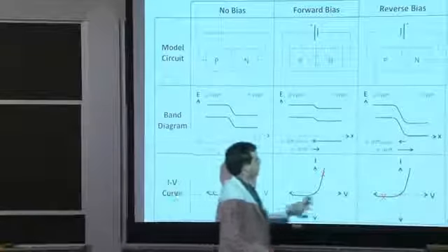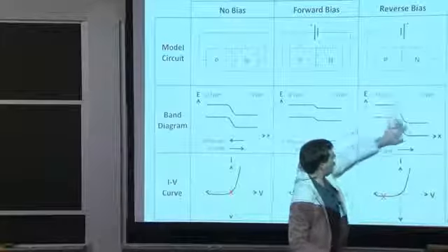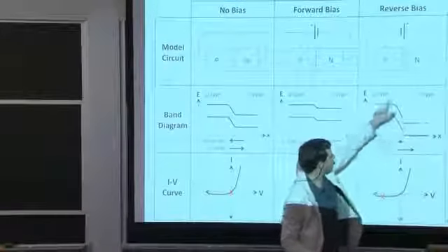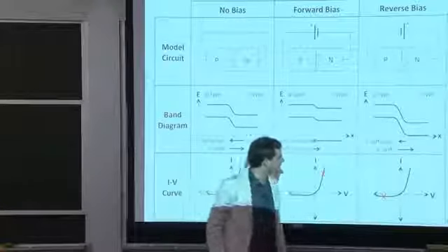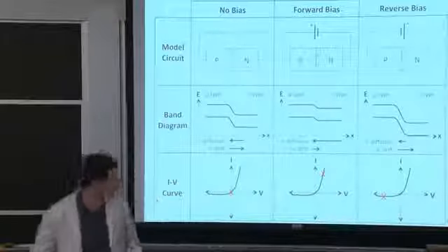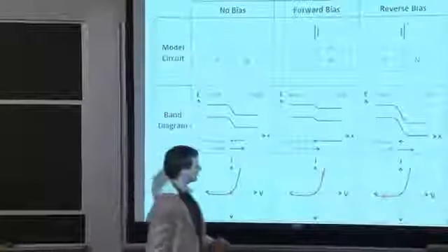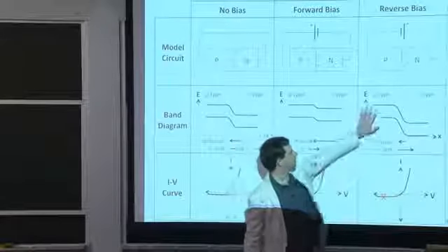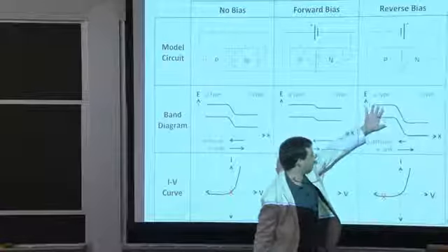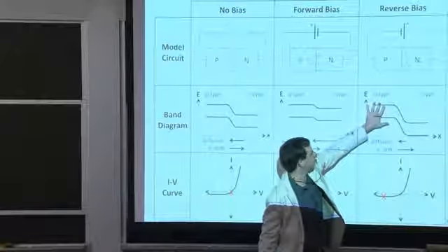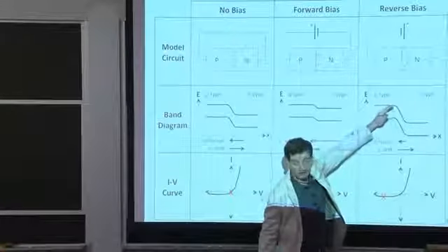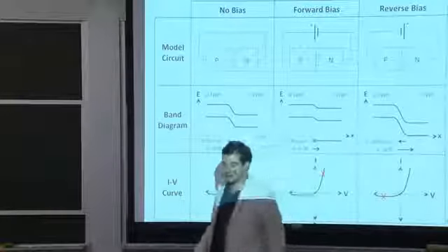As we reverse bias our device, we're increasing the barrier height for the electrons to pass over. So our diffusion current practically vanishes. And our drift current stays more or less constant all the way throughout, because there's only a finite carrier density, a finite minority carrier concentration inside of the p-type silicon, the thermally excited carriers, for instance, that are finding their way to the junction and being drifted across. And that concentration is virtually finite.